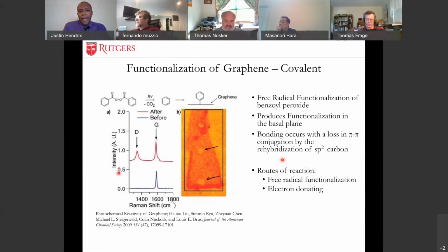And from Raman spectroscopy, we see that if we take a sheet of graphene, it has this G peak. The G peak in Raman spectroscopy corresponds to the in-plane vibrational mode. So if you have a sheet of graphene, it has minimal or almost no defects. It's going to have a high G peak vibrating on the surface.